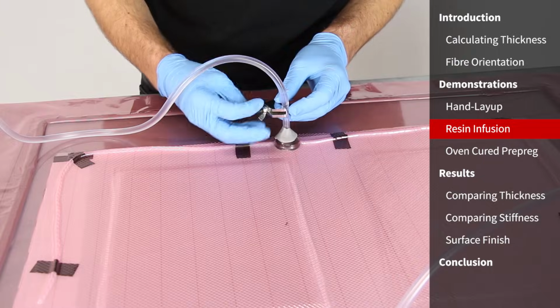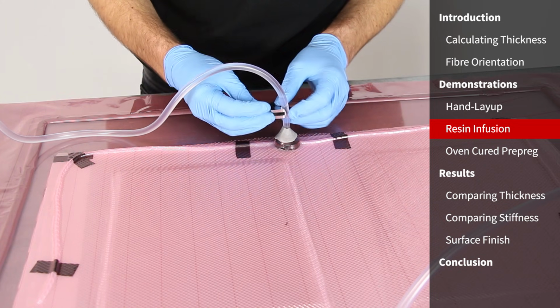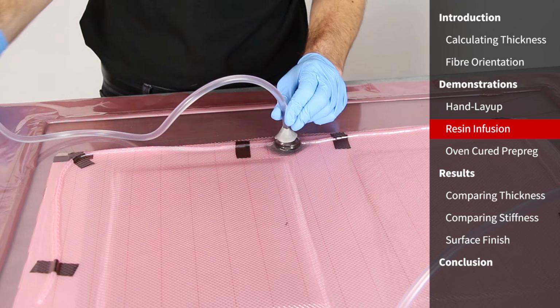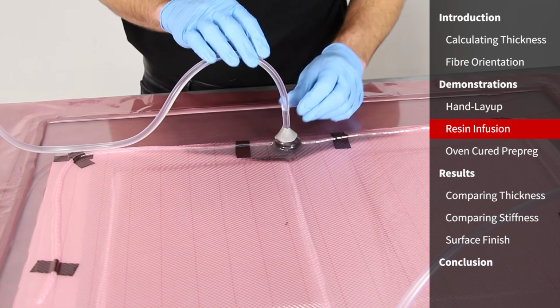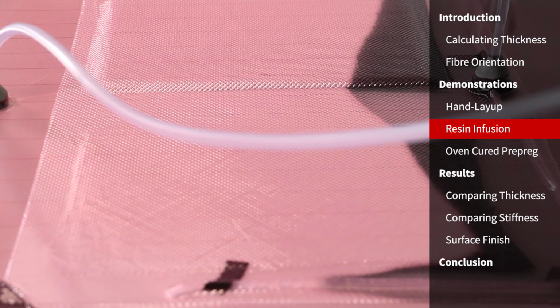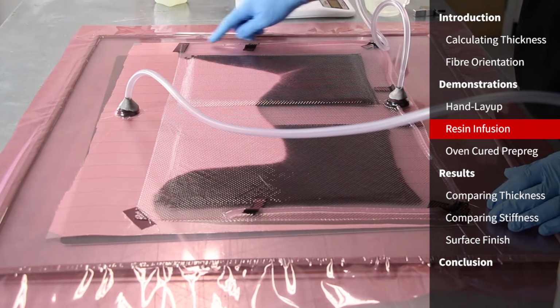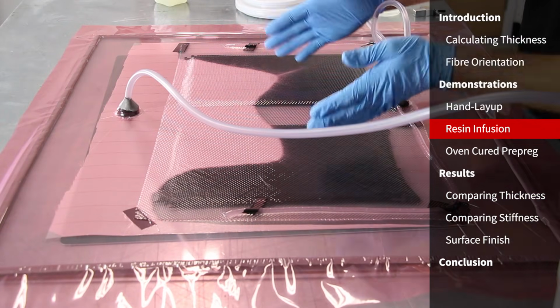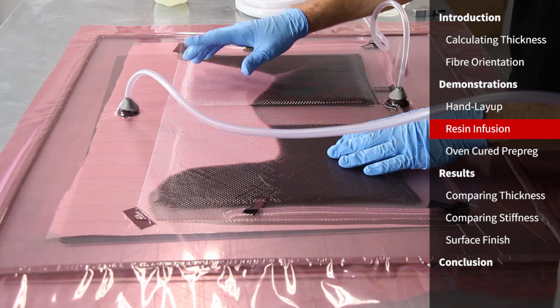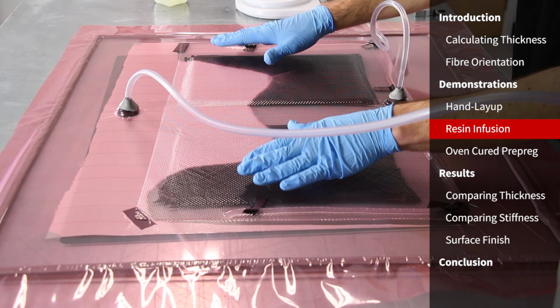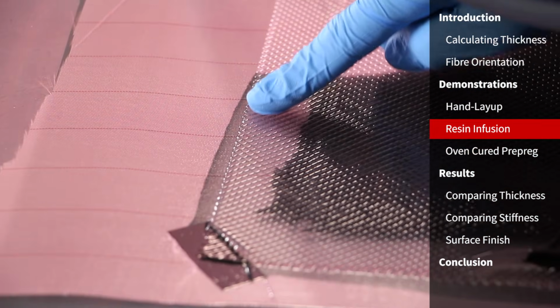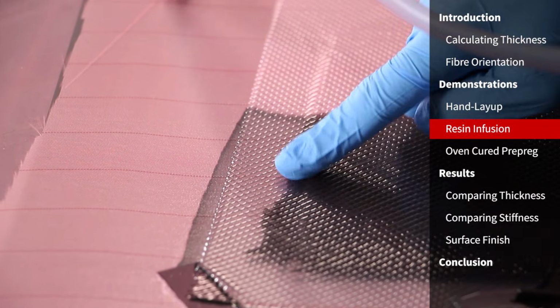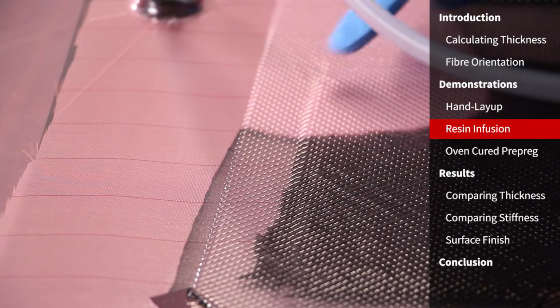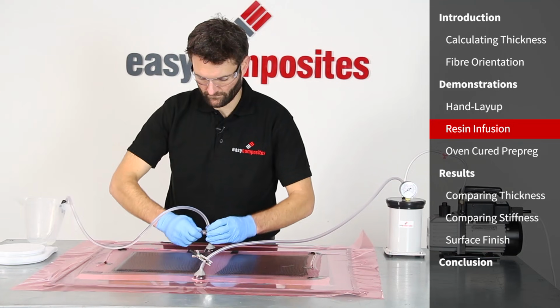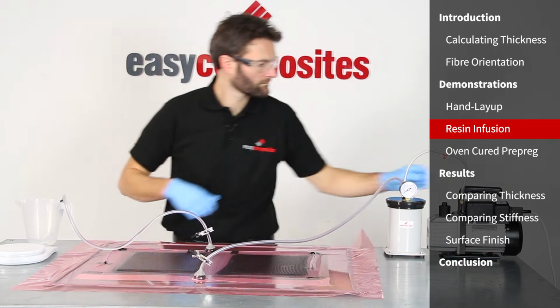So we're using our Easy Composites IN2 infusion resin, which is a special low viscosity epoxy infusion resin, and that will ensure that this infuses through the laminate reasonably quickly. We've positioned the connector in the middle, and we've got the spiral in a U shape, which is quite a common setup for a sheet like this. And you can see where you've got the spiral at the edges, that's creating this sort of U shape. And what we want that to do is reach the vacuum line on the other side last. And you can see at the top here just how effective that resin break that we set up is. Where the resin's gone over the mesh, it's advancing quite quickly, but as soon as it reaches this peel ply only area, the progress of the resin pretty much stops dead.